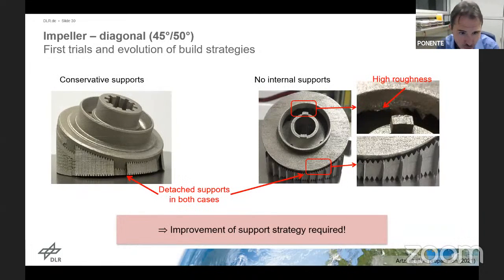On the right-hand side, from this perspective, it looks a little better, but you'll see detailed images here. Also there we had serious troubles. So in both cases, on the left-hand side, it's detachment at the base plate with the supports. On the right-hand side, it's also detachment of the supports, but this time between the supports and the part itself. And on top of that, we found with this orientation for the right impeller that we have serious issues with surface quality and precision of the geometry in this top area where we have downskin surfaces melting over the powder bed. There's this very strong inward melting here.